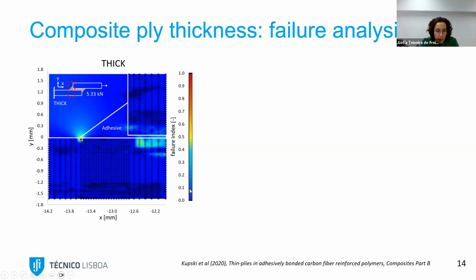And on this scale here, we see the failure index. So blue means that the node is far from failing, and red, closer to 1, means that the node is close to failure. So we applied a failure criteria in the composite in order to understand how close the stresses were to failure. For the thick one, what we see is that the hotspot, the first node to fail, is the one closest to the adhesive, and it's quite isolated. There is some also here, but most of it is concentrated here on the adhesive.